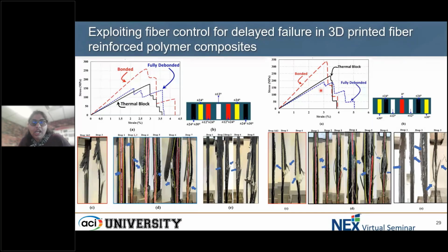And the design 3, if you look at it, the fully debonded performed very well, and the presence of the 0 degrees also had helped very much because there was some kind of brooming at the top. If you see this first image here, after that brooming happened, there is still increase in load capacity, and then there was a reduction in capacities with respect to the drops. But the highest strain was achieved for this fully debonded configuration.